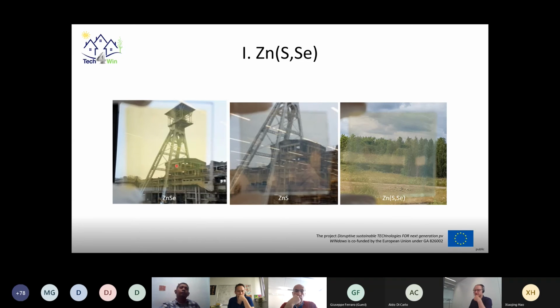So the zinc selenide was the lowest band gap, 2.6 electron volt. So it's still a bit yellowish, as you can see. Zinc sulfide, 3.6 electron volt. That becomes quite well transparent. Still somewhat grayish because of the thickness, 1 micron. And then the combination zinc sulfide selenide is somewhere in between. We see still a little bit of coloring, which we believe we can reduce by reducing the thickness later on, if possible.